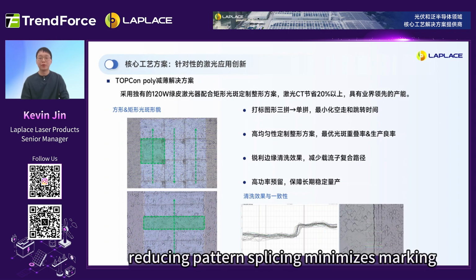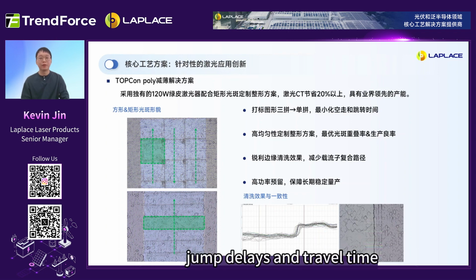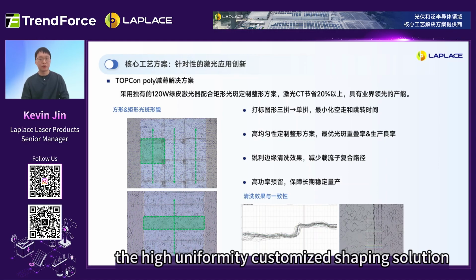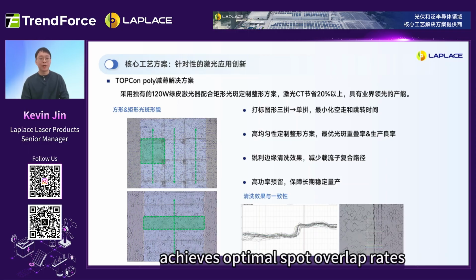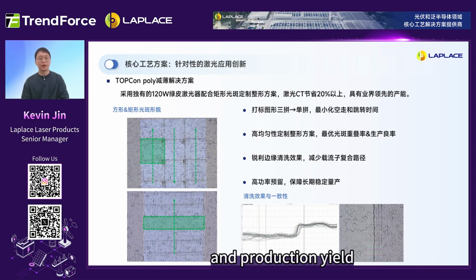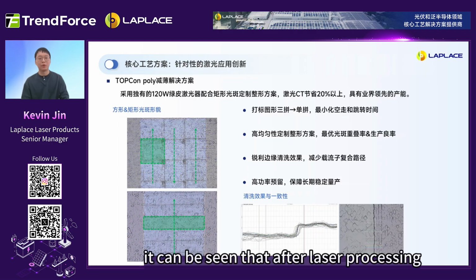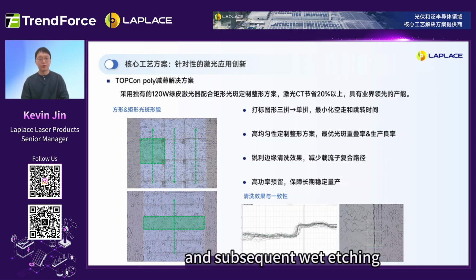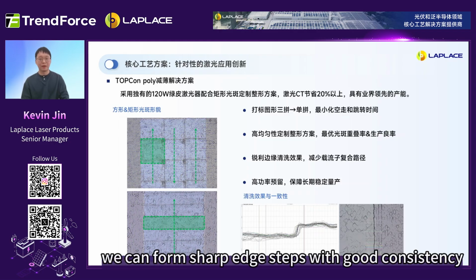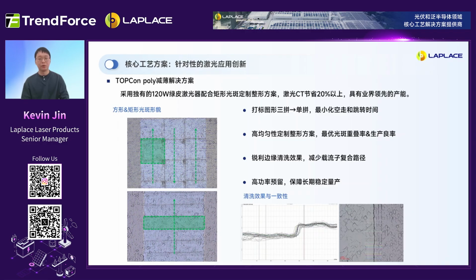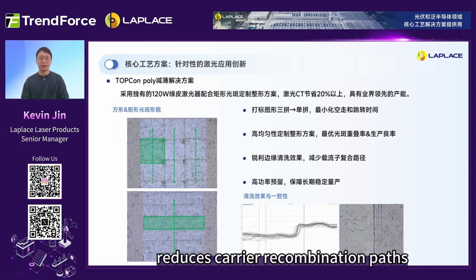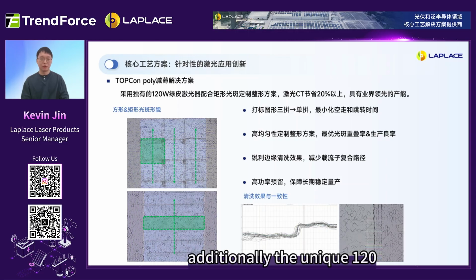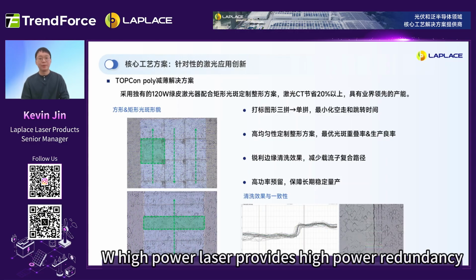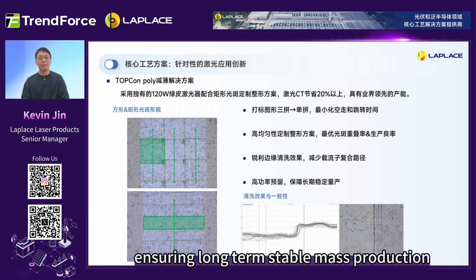Reducing pattern splicing minimizes marking, jump delays, and travel time. At the same time, the high uniformity customized shaping solution achieves optimal spot overlap rates and production yield. In the diagram below, it can be seen that after laser processing and subsequent wet etching, we can form sharp edge steps with good consistency. Sharp edge definition reduces carrier recombination paths. Additionally, the unique 120W high-power laser provides high-power redundancy, ensuring long-term stable mass production.